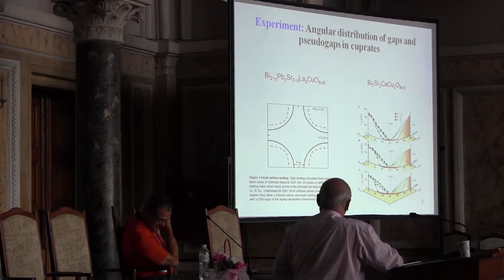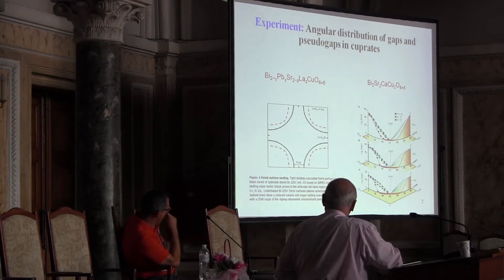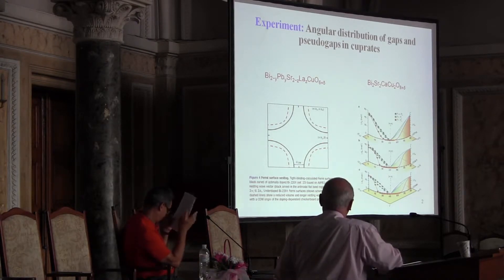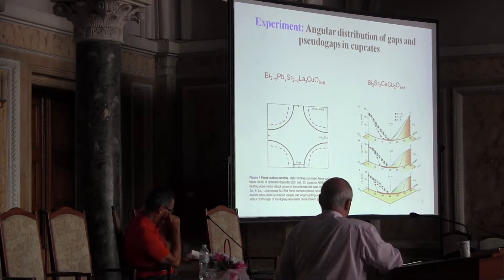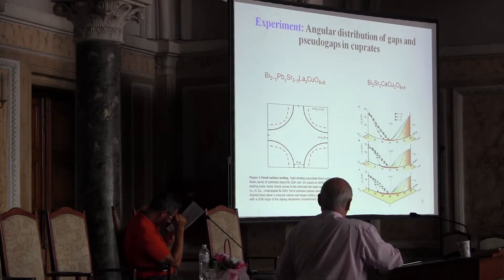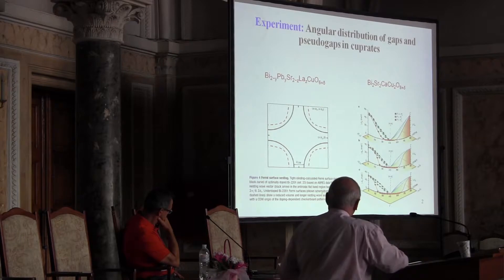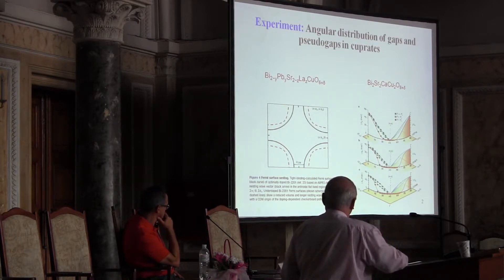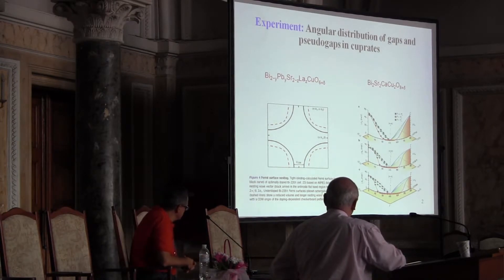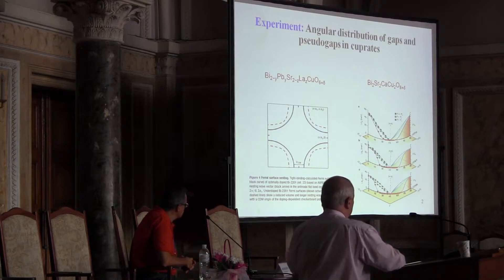These are very complex oxides. The gap appears at some points of the Brillouin zone, and this gap is connected to the nesting properties of the Fermi surface. This gap is a dielectric one, and in real space it is reflected as some shifts of atoms which were first discovered by Peierls in 1930. This is called Peierls transition, and all such phenomena are called charge density waves.